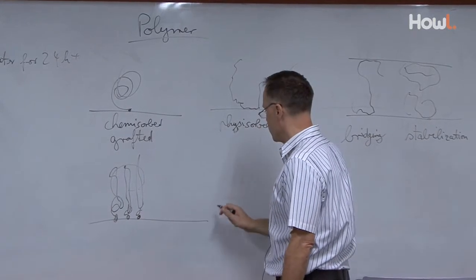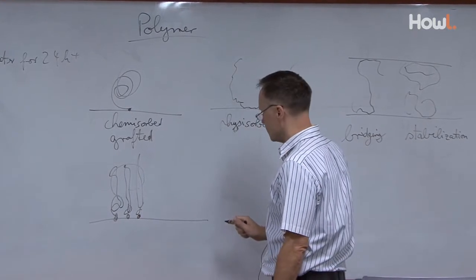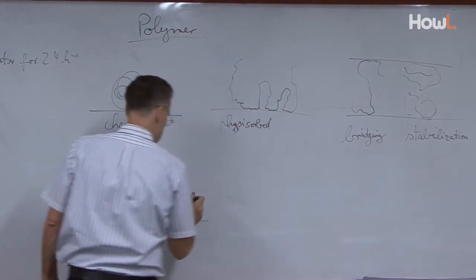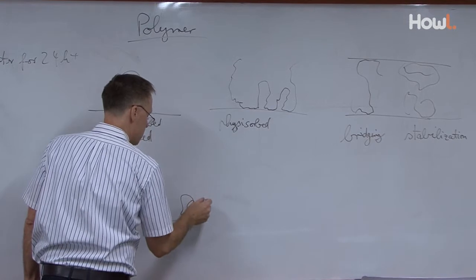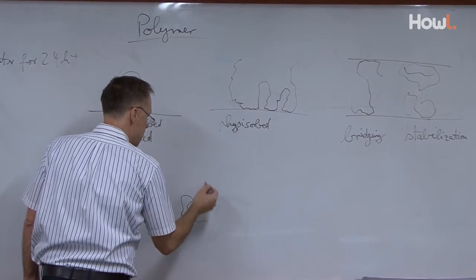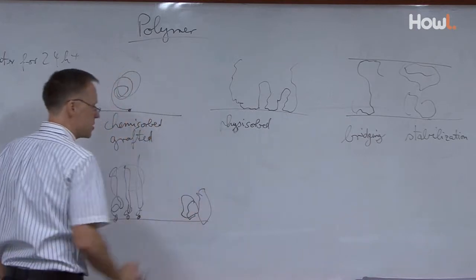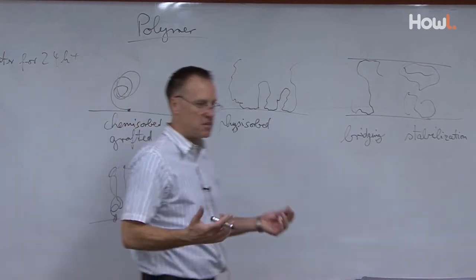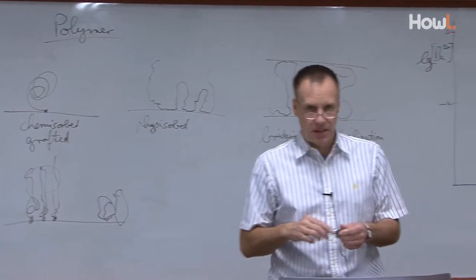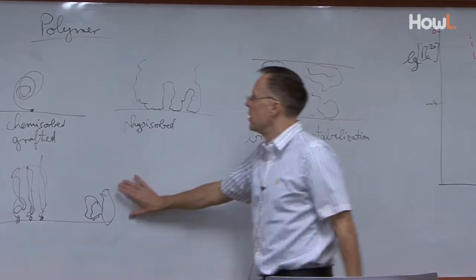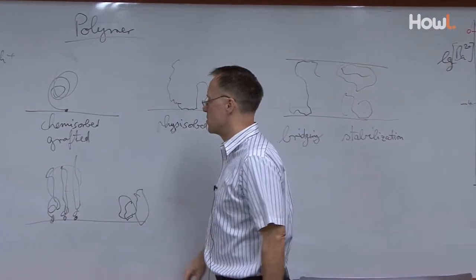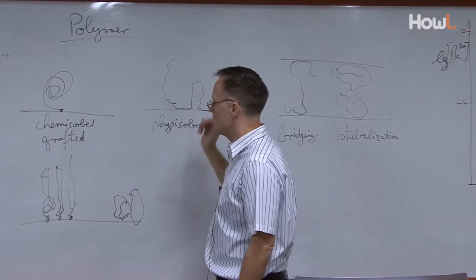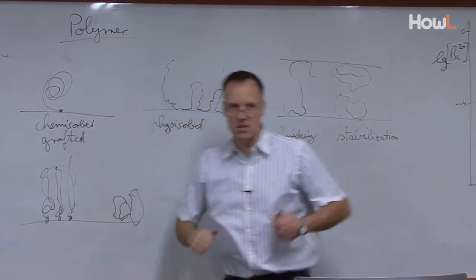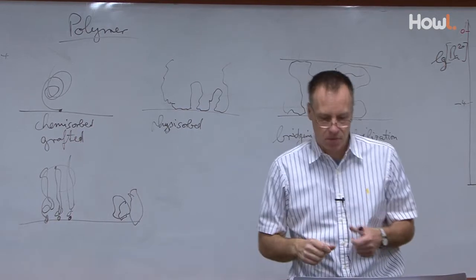If you do work with physisorb, it would be the same thing. You try to attach as many physisorb molecules as possible. The challenge is then to really get them to also extend. And that is a challenge to do with physisorb. Typically, you can't do this. They typically do not extend much beyond what the physisorption does automatically. You don't have much control over this. So this chemigrafting is actually some possibility to give you the maximum repulsion.